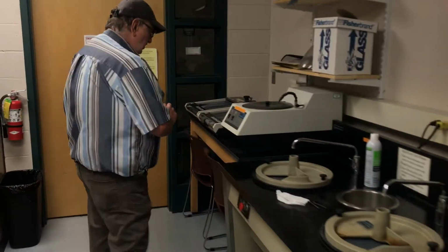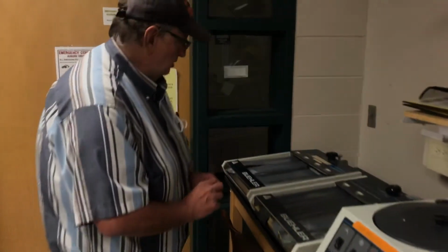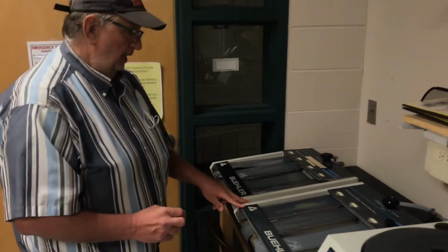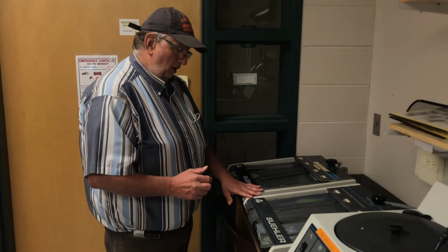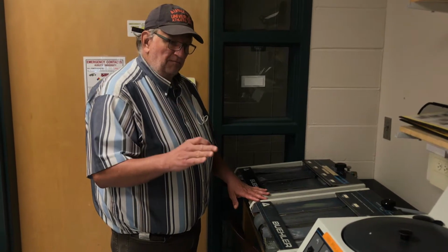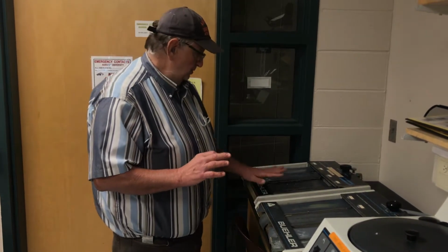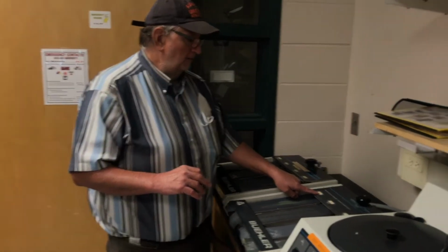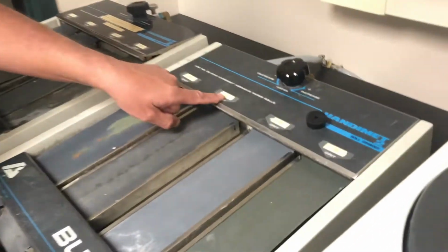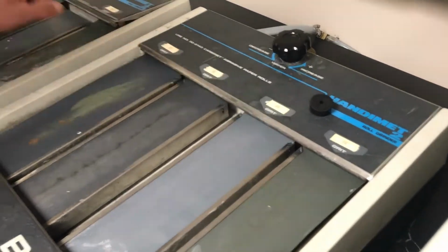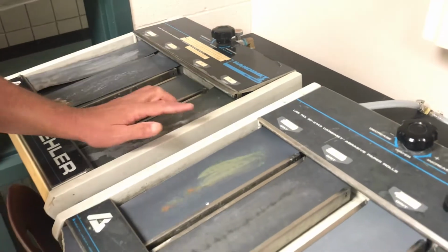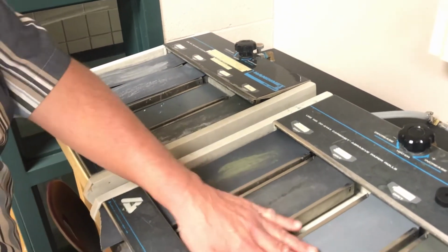Now, for the next step, we have a manual polisher. We have two manual polishers, and by the way, what's happening here is that you're going from very rough polish to finer and finer polish until you end up with a very nice polish, hopefully, okay? So the next step here is to use the manual polisher. This one starts out at 320 and increasingly gets finer and finer, 400, 600, and 1000. They're both the same, okay? Make sure there's paper there in each one.